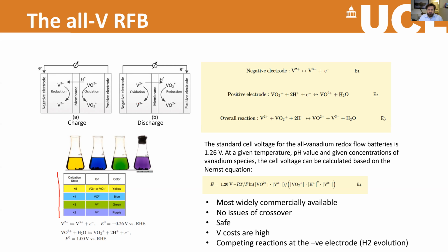One of the key benefits of the all vanadium flow battery is that we're using vanadium in both the negative and the positive electrolyte. So although we try and reduce the amount of active species that cross over into different electrodes or electrolyte chambers with a membrane, there is still some crossover of species that happens. And when that happens, it reduces the capacity of your battery effectively. But in the case of the all vanadium battery, because we have vanadium species on both sides, we can actually recharge the battery in terms of rebalancing that amount of active species in the positive and negative side, because we can just electrochemically oxidize or reduce that vanadium species that shouldn't be there to its proper oxidation state.